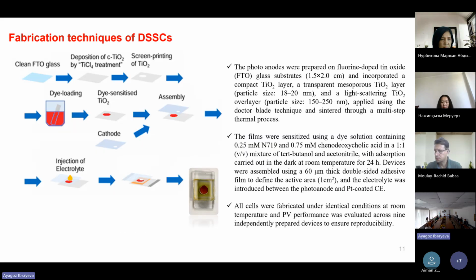And further, after successful synthesis of this material, we fabricated the solar cell. Briefly, we clean our FTO glasses, then apply blocking layers, then by the doctor blading technique, apply mesoporous scattering layers of titanium paste. After that, photoanodes were soaked in the dye for 24 hours. After that, they were assembled with the platinum counter electrode and electrolytes were injected. All devices were fabricated in identical conditions. And for reproducibility, we always make 9 cells.